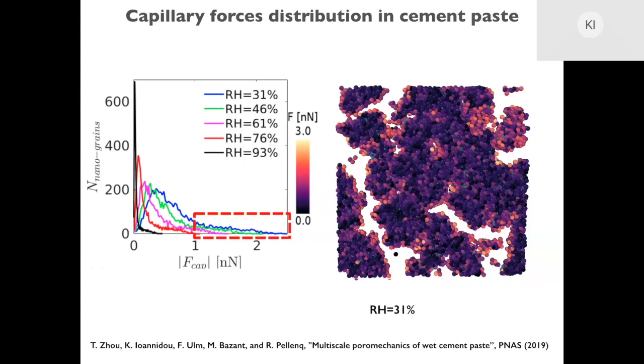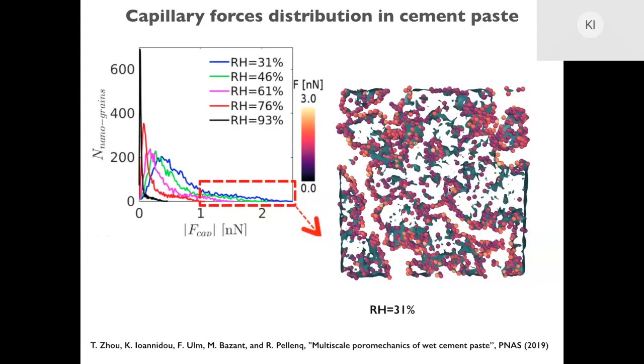Let's see where this part of the tail is localized. So let's see where the highest capillary forces are. Here is the same snapshot you saw before, but now we only focus on the particles that are within this box, so on the tail of the distribution. And this green interface that you see on the snapshot is basically the interface between the solid and the pore. So all the particles that have strong capillary forces are the ones sitting on the surface of the solid between the pore and the solid, and especially the ones in junctions between small pores and larger capillary pores.